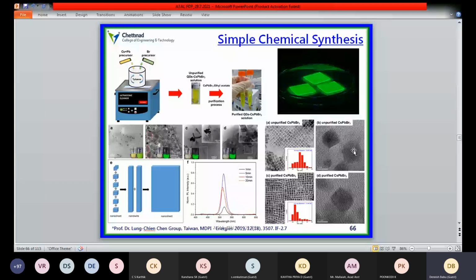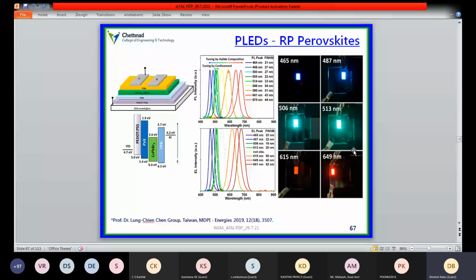This is the work for which we made a tie-up with a Taiwan professor to fabricate devices for butyl ammonium and cesium-based perovskites. We prepared two systems, organic and inorganic perovskites. For the organic cation, we are using butyl ammonium. For the inorganic system, we are using cesium lead halide systems. If we couple this organic and inorganic metal halide system, it can easily release emission at a particular wavelength, like the exact photoluminescence wavelength depicted here. The professor's group fabricated the LED device and tested it in their laboratory. We sent 3 samples, and they exhibit blue, green, and red color emission. These are some of the achievements we have made in